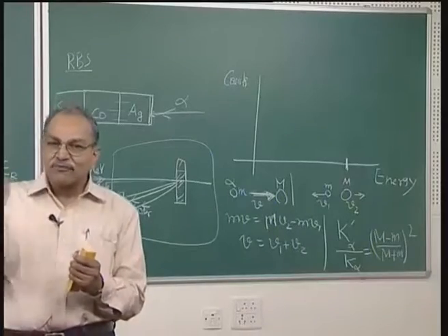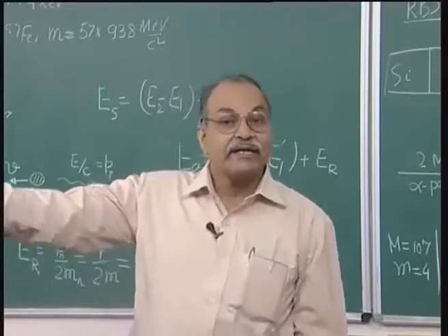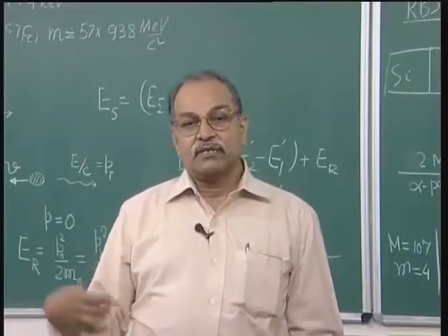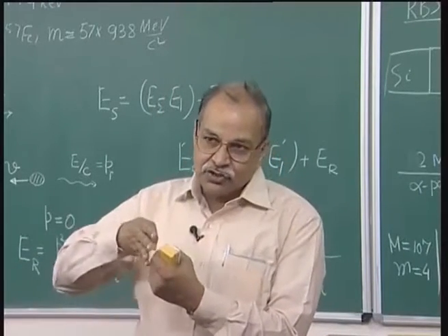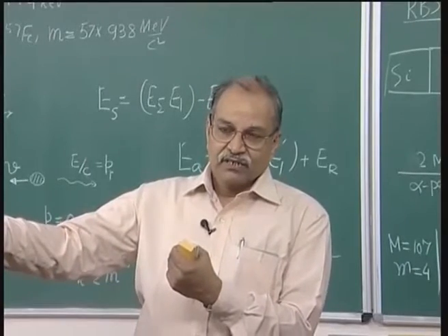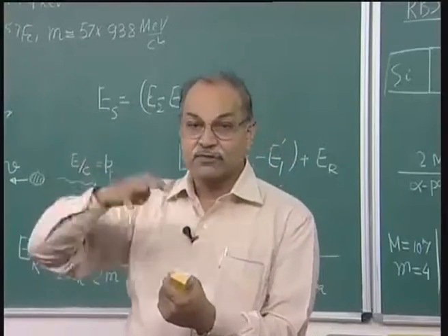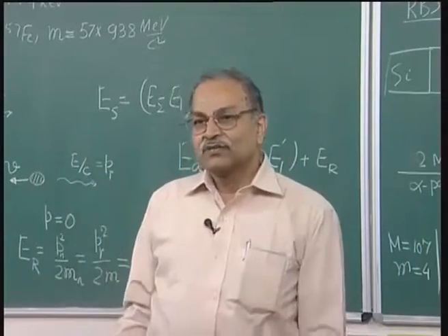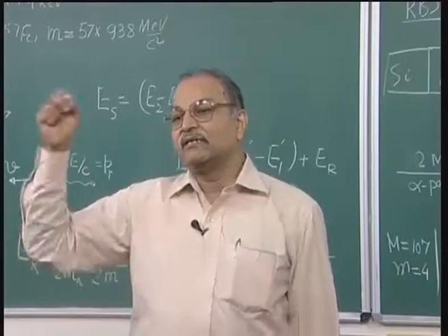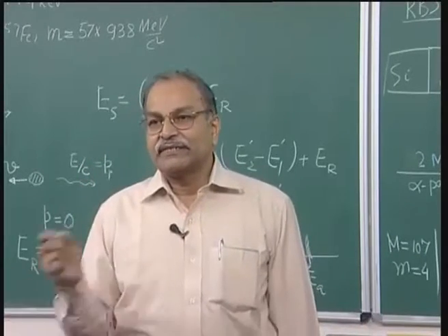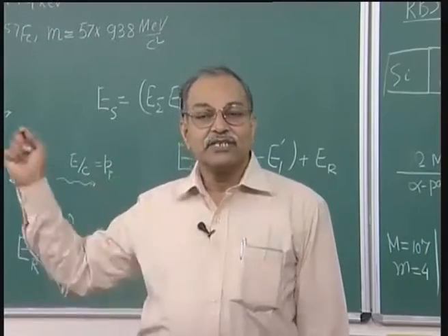If they are scattered from the surface, this is the energy, and if they go deeper inside and then get scattered from a silver nucleus, then during this transit into the material, they are continuously losing energy because of their interaction with all those electrons present there. So if the nuclear encounter is at a depth, then at that encounter the incident energy is already smaller than the initial beam energy.